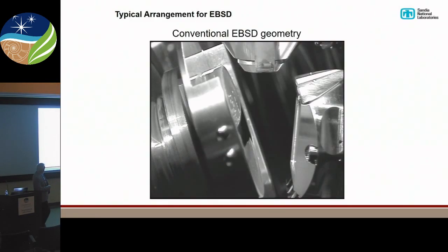But actually, with a modern system, you can run this without hitting things too often. And you can use metallographically polished sections. This is a large piece of tantalum. The diameter here is about 1.5 inches on that sample. So we can put rather large samples in, and that's limited by the microscope.